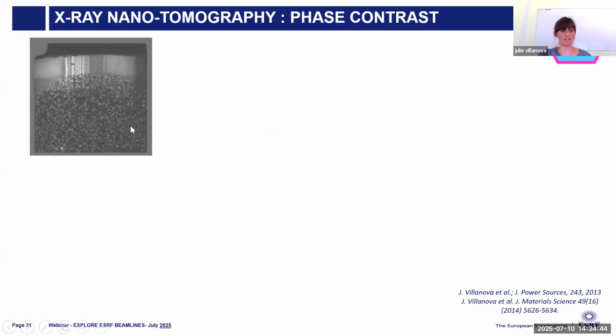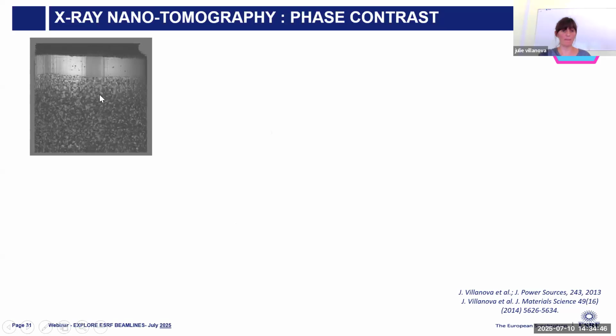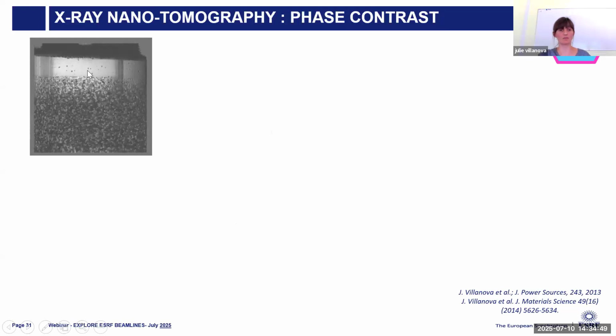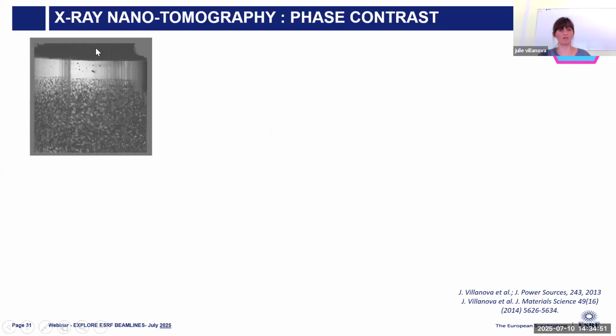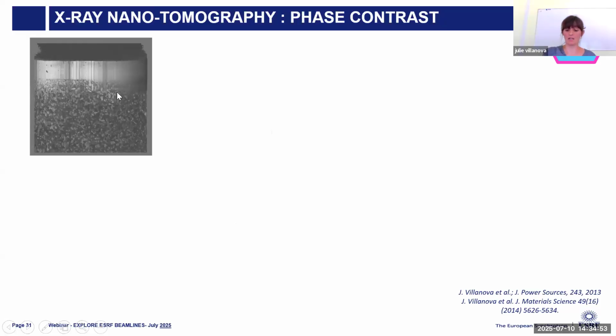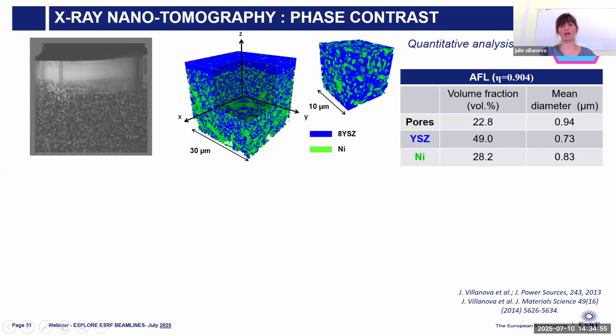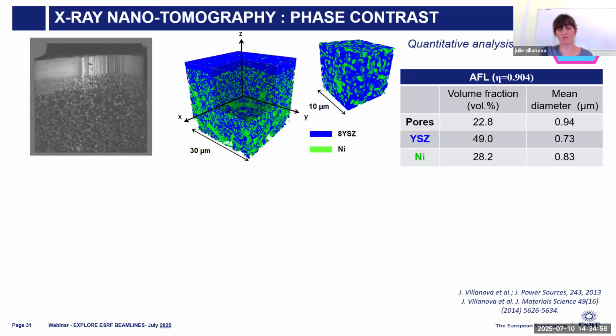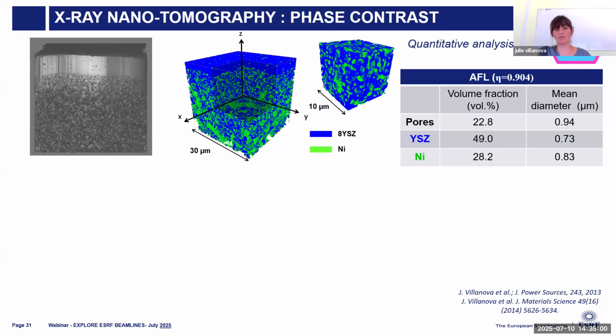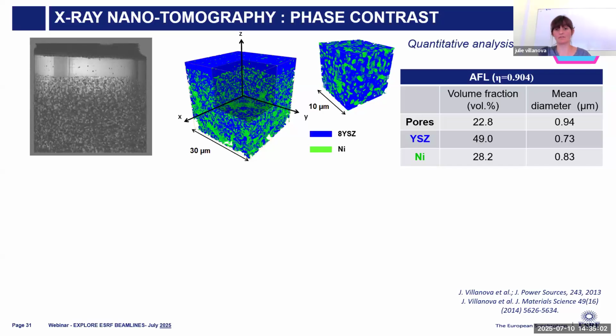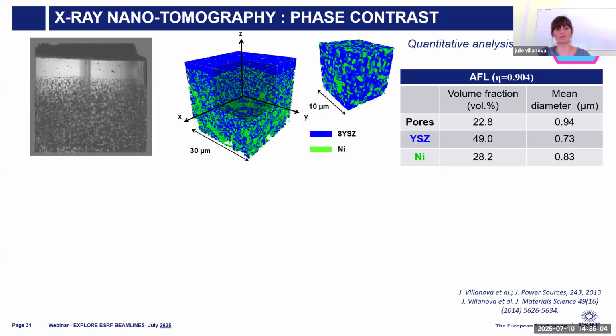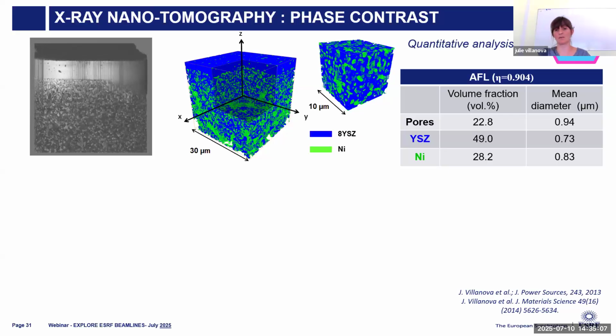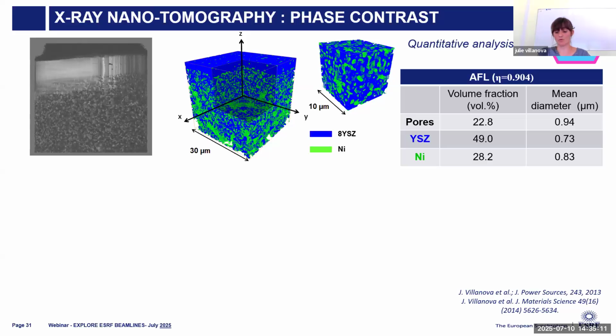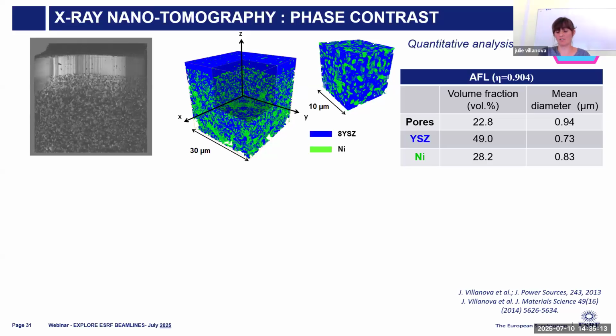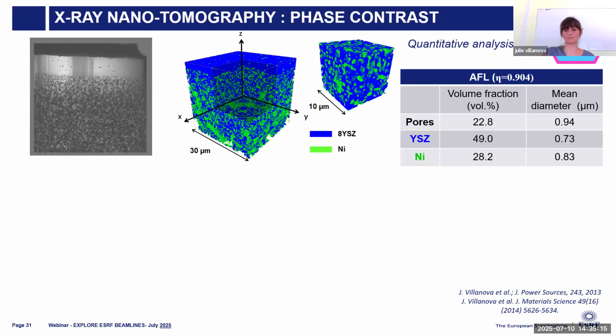So what does it allow us to have? Well, nice videos like this where you see your sample in 3D. This is a solid oxide cell. You see we have the dense electrolyte, the 2 porous electrodes, but not only, and that's the most important, we can actually perform quantitative analysis on those volumes, as for example looking at the different volume fractions of the phases or the porosity, look at the tortuosity of those pores, determine the representative volume element, and also calculate other intrinsic properties you can have in your sample.